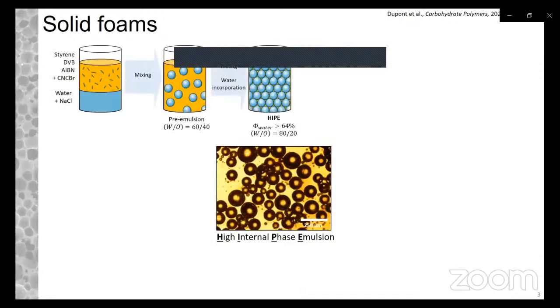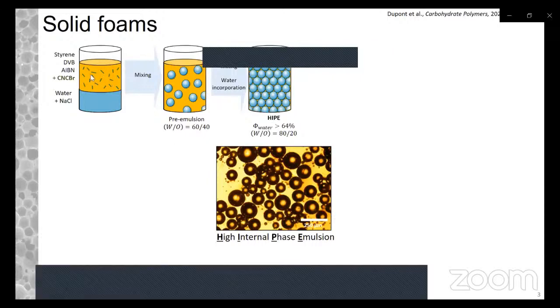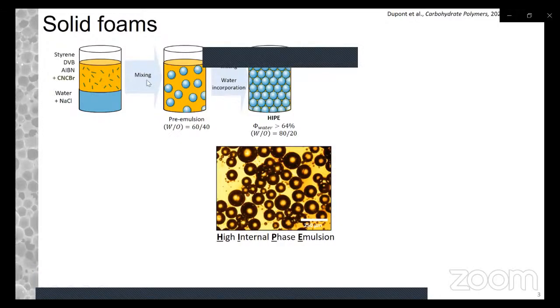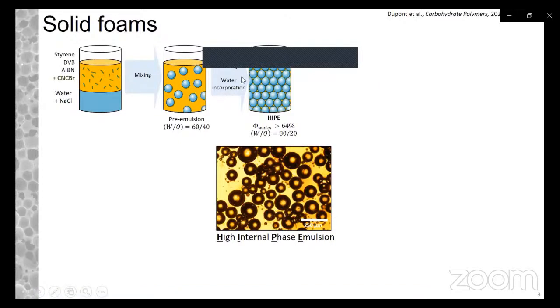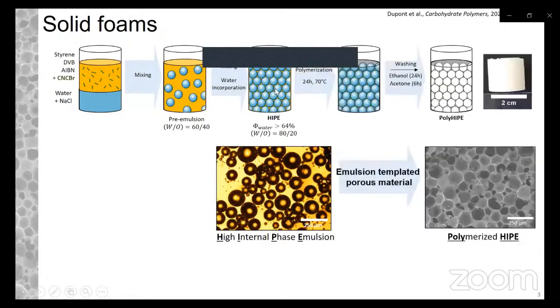The first type of material we succeeded in synthesizing were solid foams. Regarding the process, we dispersed the hydrophobic CNC into an organic medium, which contains the monomers, styrene and divinylbenzene, and we disperse water inside by mixing. So we obtain the inverted emulsion, the water droplets inside the organic medium. To obtain a solid foam, we have to increase the water content above 64% to obtain a high internal phase emulsion, which is called HIPE. Then we are able to polymerize the continuous phase containing the monomers, so solidify it.